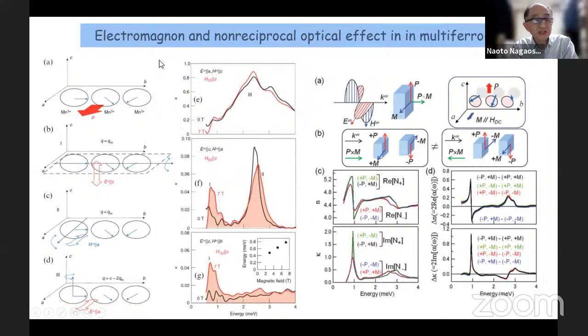And in addition to this static ground state polarization, you could have magnon excitations. Because the magnetic structure is associated with polarization, the magnon is also associated with polarization fluctuation. So then the magnon excitation can be excited by the electric field of light, not the magnetic field of light. So by changing the polarization of light, you can identify which mode corresponds to the fluctuation of this polarization P, namely the electromagnon of this cycloidal structure.